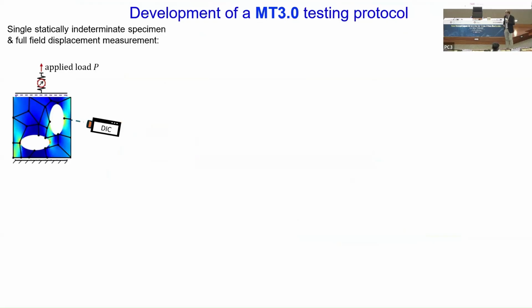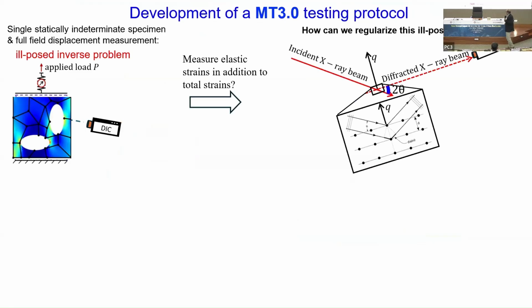So this is the traditional technique. You're only doing optical measurements. And now these are these sort of ill-posed inverse problems. How can you regularize this ill-posed problem? Well, there's one thing you can do: in addition to measuring these strains, suppose I actually measure the changes in the atomic spacing. Changes in the atomic spacing will then tell me the elastic strains, because that's what's actually generating the stress inside the materials, because the atomic bonds are being stretched.